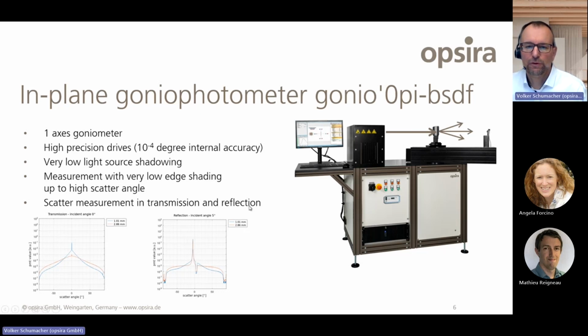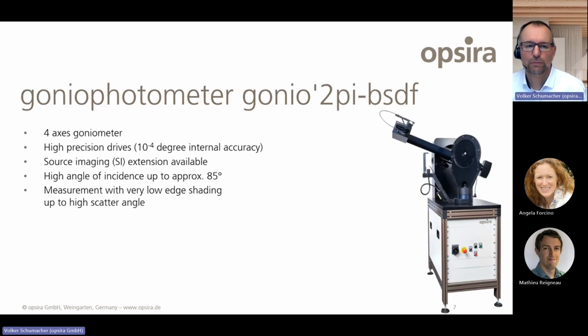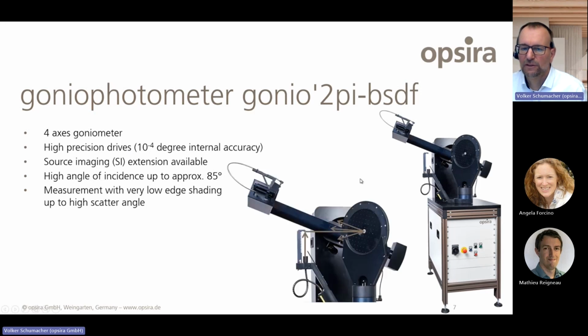That's the in-plane goniophotometer, and then we have the 3D goniophotometer. This is a 4-axis goniometer. We use in our goniometers high precision drives. There are servo drives with a very high internal accuracy. Also, we are able, based on the setup, to make a very high angle of incidence. We are very free here how we can bring the light to the sample, and also in respect to the measurement. We can measure to very high angles and get only a very low edge shading.